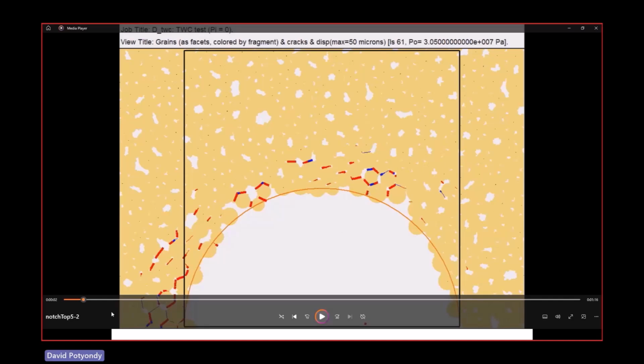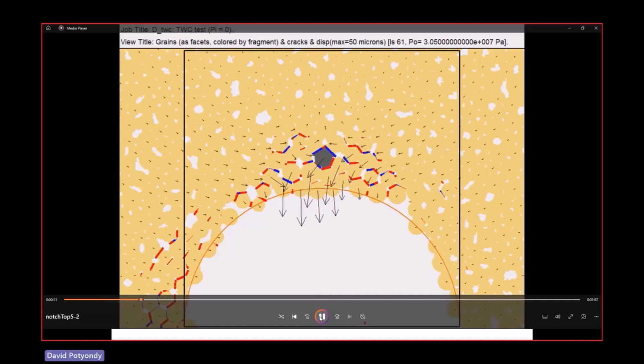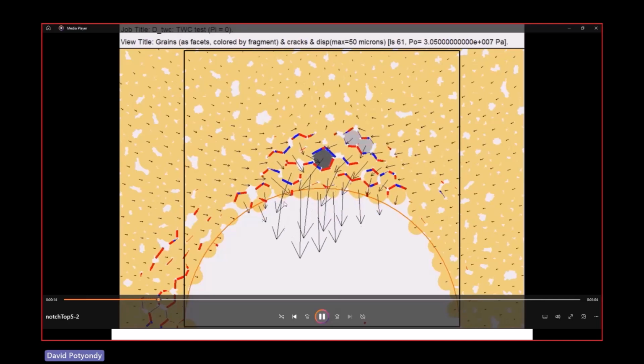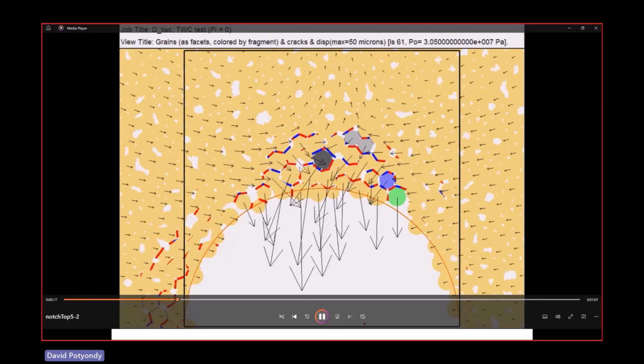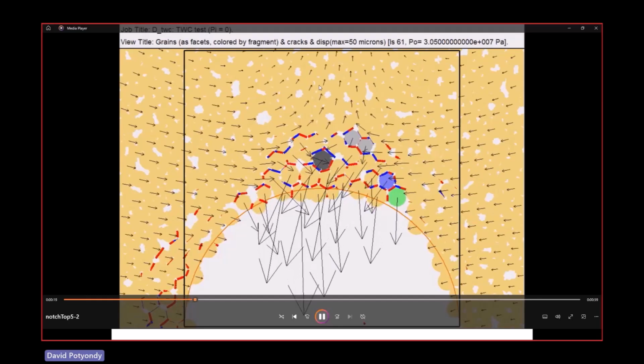Now, as we apply this load from 30 to 30.5 and watch the system readjust, we set all the displacements to 0 as a reference, and we just want to look at the deformation and damage that forms due to this little increment of load. You will see this notch begin to develop, and the displacement field begin to develop. You can see how this notch is dilating inward, and because this is softer now, the displacement field moves upward.